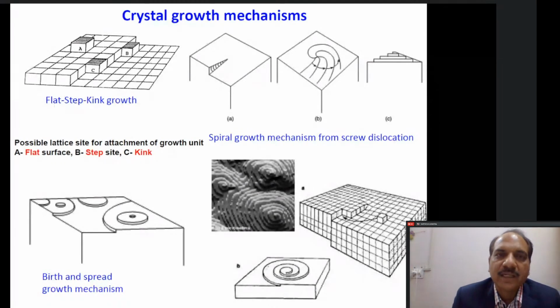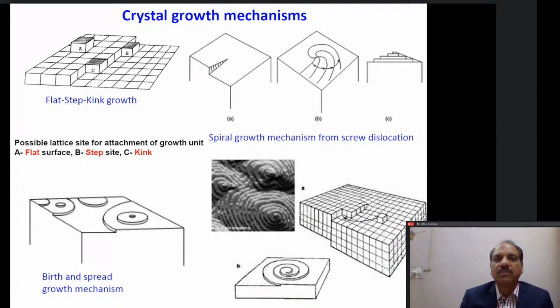We all know that there is a dislocation mediated growth. There is the Burton model of growth, the spiral growth mechanism, which is basically a dislocation mediated growth. And we also know that there is a flat step and kink model of growth. So we thought if we can do some experiments which can validate these models, that would be very wonderful. So we initiated some activity long back on these aspects, and because our forte was optical and laser-based techniques, we thought of doing some sort of imaging studies, so that we get the image of whatever crystal is growing, through these optical techniques.